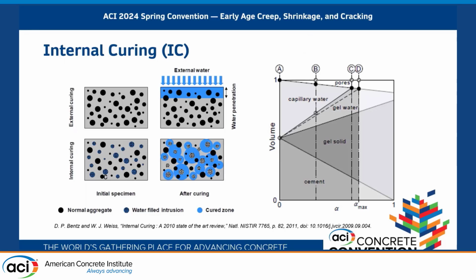So going back, really quick, refreshing our minds about what internal curing is: we're going to try to provide a source of water that is embedded in the concrete during the mixing process. And that helps with having a more homogeneous distribution of internal moisture that can help with the reaction of the cementitious materials, and that can also have implications on the volumetric changes that concrete materials have, especially at early ages.